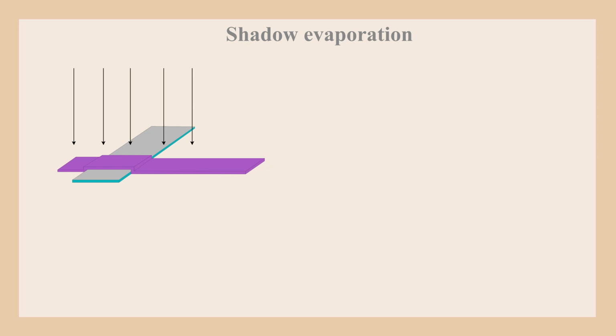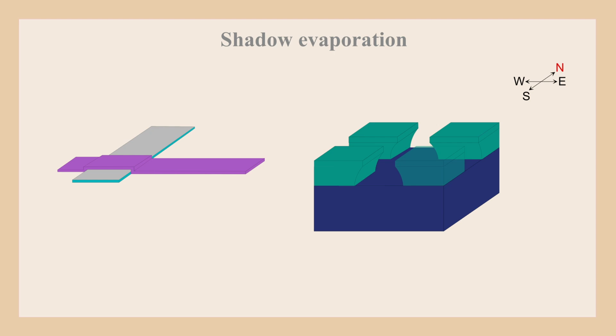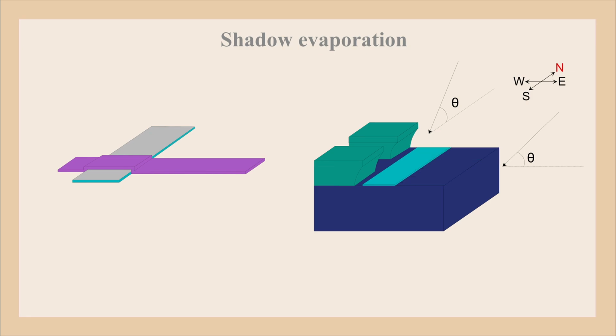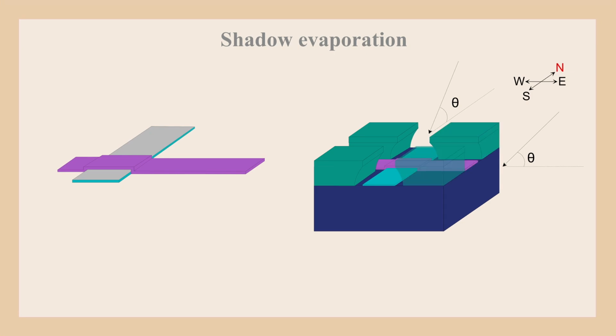And what that does is that if you have a cross pattern like this one here, if we deposit from the north direction at an angle of say 45 degrees, then the resist stack that is behind the west-eastern trench will block any metal from depositing along that direction, and only the north-south electrode will be deposited. If we then deposit the second electrode from the east, then the north-south trench will be protected, and only the west-east electrode will be deposited. Afterwards, we can repeat this exercise for the patches at their corresponding rotation.